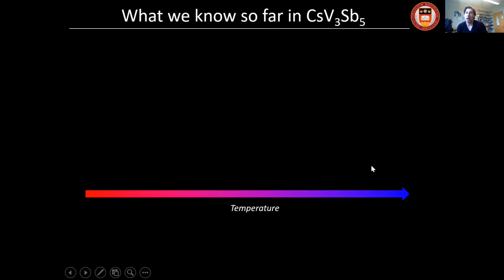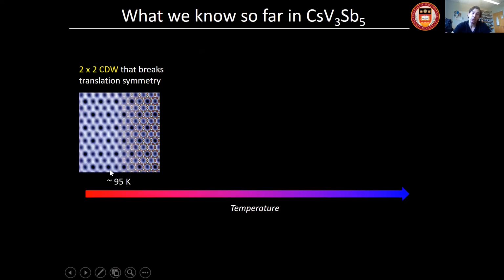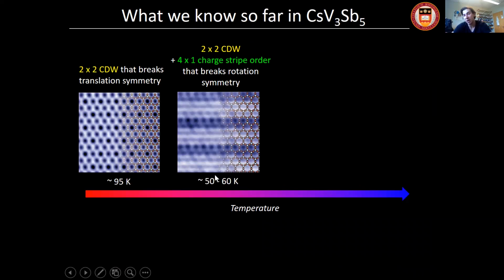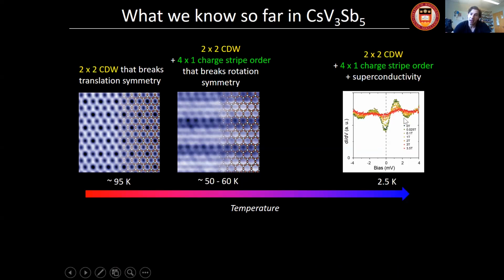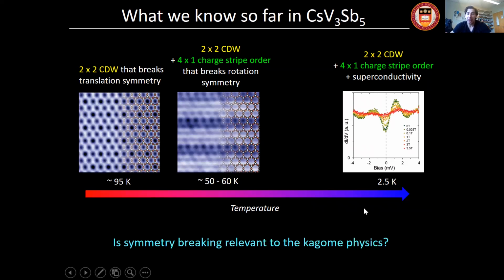Okay, so I've shown you a lot of different transitions and a lot of different states, so I just want to summarize what we know so far. At about 94, 95 Kelvin, this material transitions into a 2x2 charge density wave state that breaks the translation symmetry. Then at about 50 to 60 Kelvin, we get an additional charge order that breaks the rotation symmetry. And then at 2.5 Kelvin, we enter the superconducting state with these two charge ordering states carried over as well. So the natural question that arises is, to what extent is this charge stripe order and the rotation symmetry breaking that's clearly there based on STM really relevant to the Kagome physics?